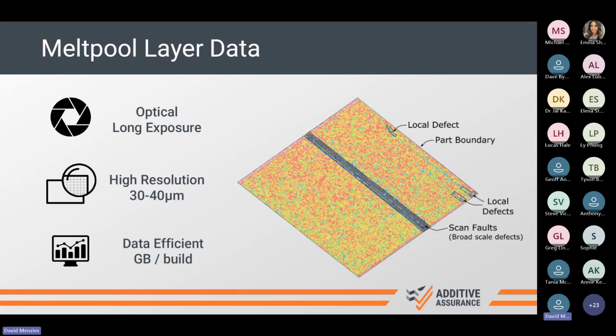But moving down to the nuts and bolts of it, we're looking at that melt pool layer. So we're resolving that build plate in a long exposure mode. We're taking that entire layer of information across those 8 cameras, stitching it together and getting a resolution image of 30 to 40 microns per pixel. That variation is really dependent on the industrial design of the equipment that we are operating on, depending on how close the window is to that build plate. So what we can see is effectively all the different types of defects across that melt pool layer. That is a false color image. We are seeing black and white through our lenses, but it's obviously easier to see that in color as an operator.